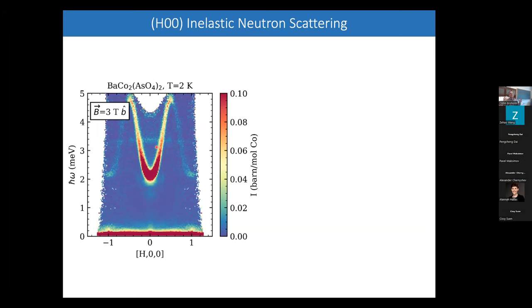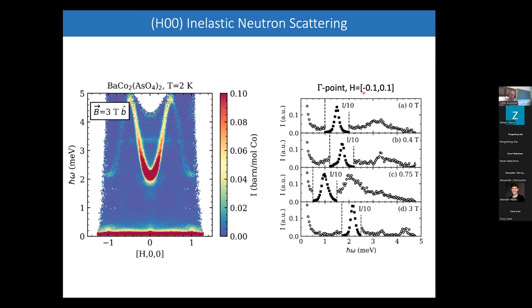But then once I get to 3 Tesla, all of that pretty much is suppressed, and I now have simply the dispersion relation that you expect for an anisotropic ferromagnet. And as I now increase the field more, then this mode is driven to even higher energies. Here is a plot of the spectrum of scattering as a function of field. And so this region here, I've had to divide by 10 because this is really an immense peak. But you can see additional, all of this is real magnetic scattering in the system.